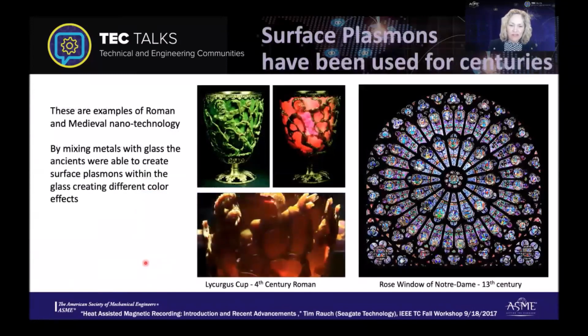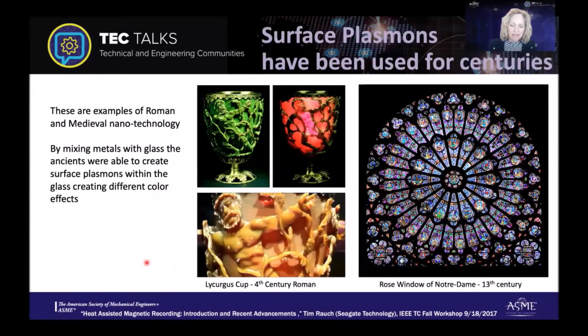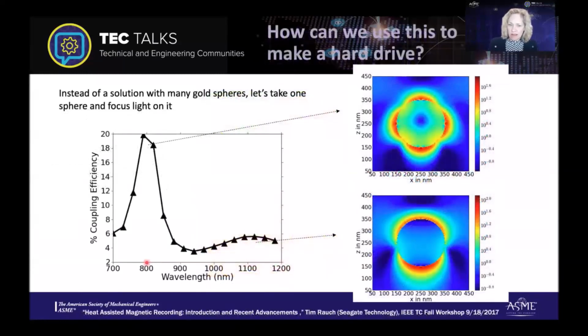This had been used for many centuries. Small metallic particles in glass actually had different effects on the transmission and reflection of light, and have been used for centuries. But what if instead of taking glass with a small gold sphere, we actually just took one gold sphere, just one sphere, a couple 100 nanometers, and focused light on it. If we look at those wavelengths of light and the interaction with this gold sphere, at certain wavelengths, you can get very, very efficient coupling into that gold sphere. And you can see the electromagnetic field then around the gold sphere.